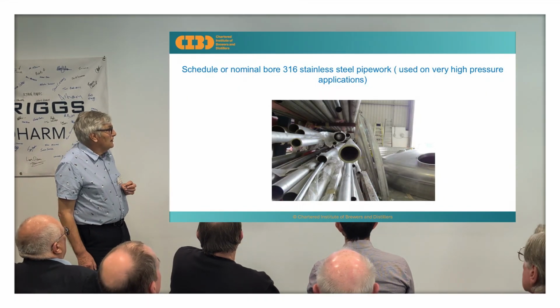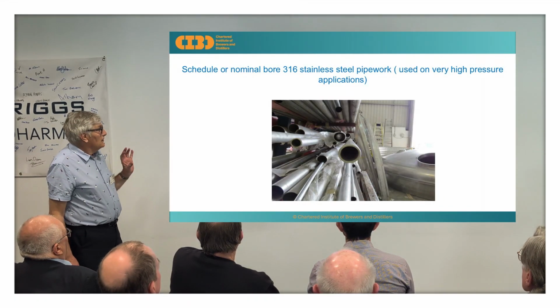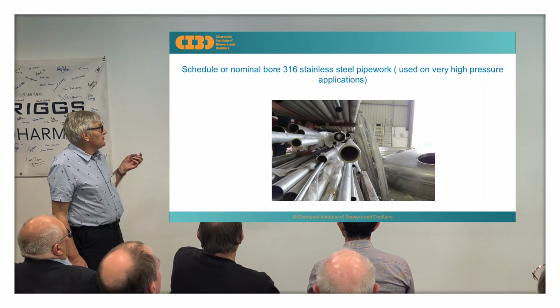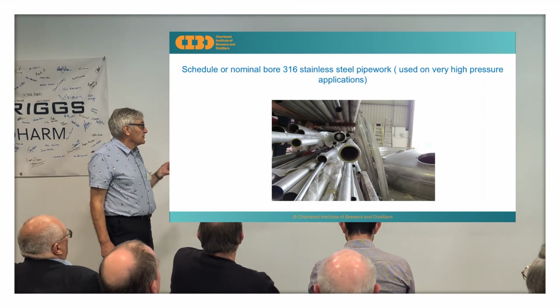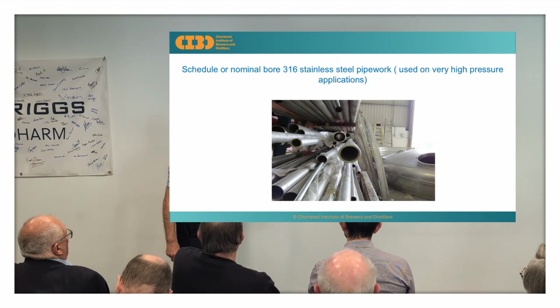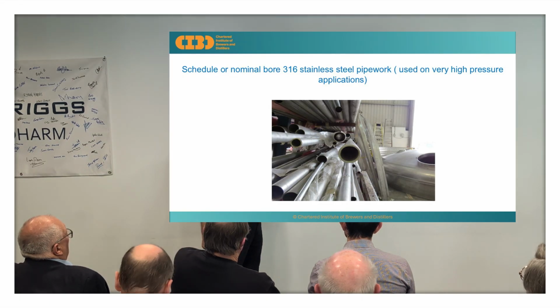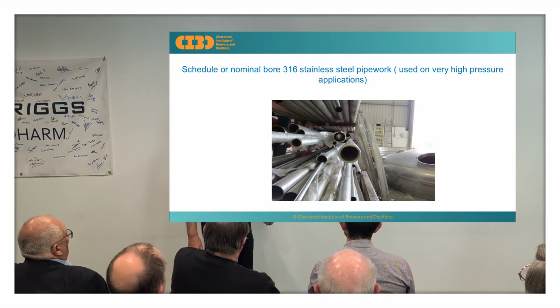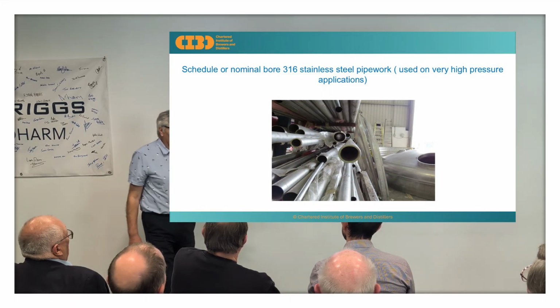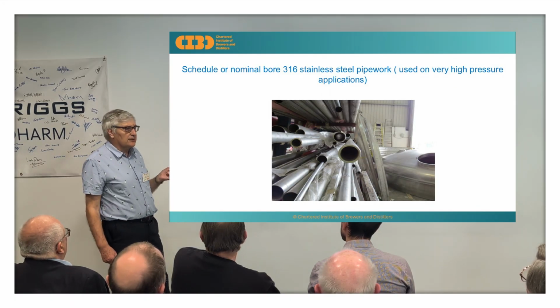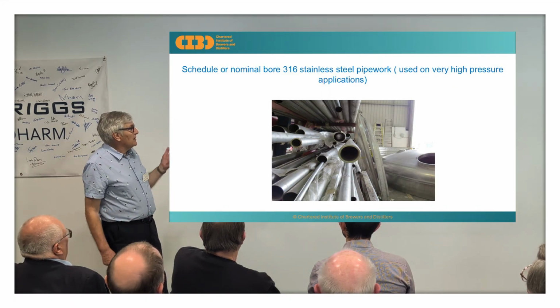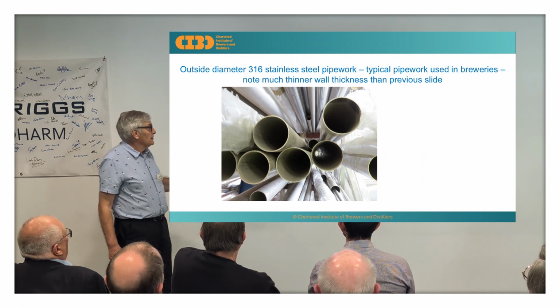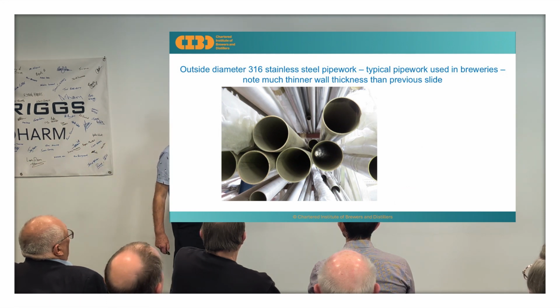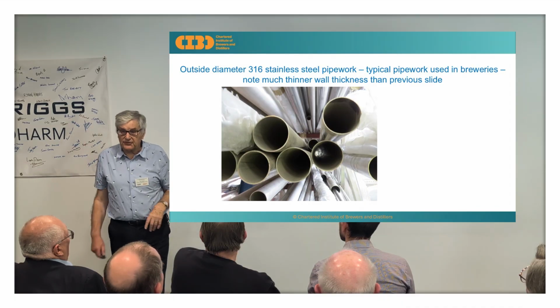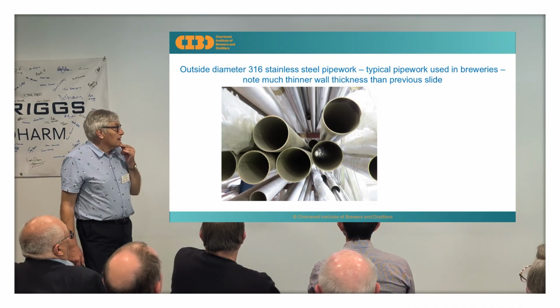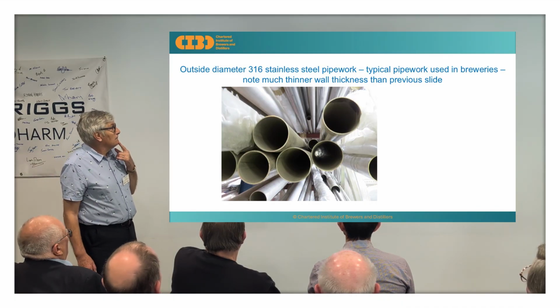And this, again, is an idea. This is a nominal bore 316 stainless steel. What I'm pointing out here is this is for really high pressure applications. You wouldn't normally use these in the brewery. The brewery can get away with the OD thin wall stuff, which is about 2.5 millimetres thick, and that will stand most of the pressures and temperatures that we want.